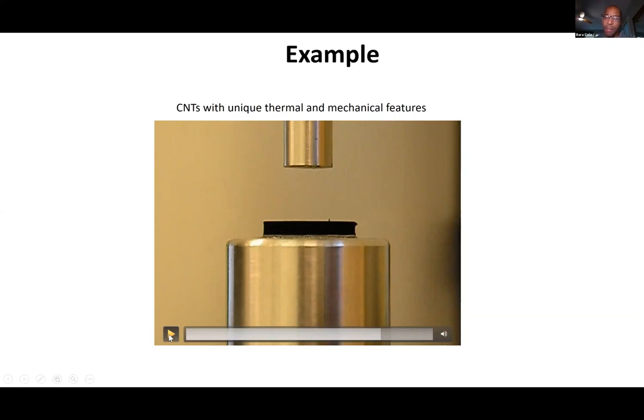And so what's unique about that deformation is that it's local. And that's important because if you want to have a dry material, you want to get away from liquids that have problems with addressing thermal interfacing with the current industry trends. Specifically, as package sizes get larger, the thermal expansion causes more shear stress in the interface, and greases and PCMs or phase change materials tend to lose reliability. They tend to pump out more, shear out more. And so as you have larger packages, having a dry material is important.